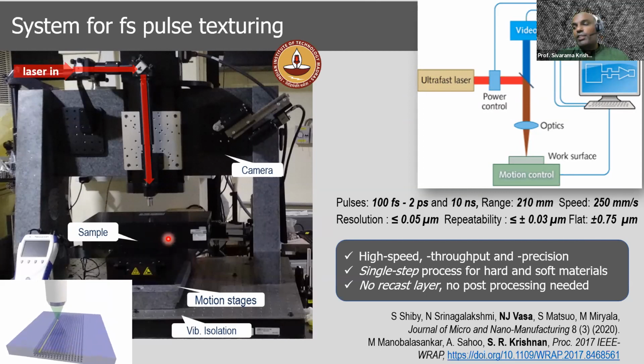These stages may not be very visible on this view graph owing to the fact that they are all black in color, but it's just a conventional XYZ stack. The same schematic is portrayed more clearly on the top right box. So we can vary pulse widths going all the way from sub 100 femtoseconds to 2 picoseconds. In some cases, we have used nanosecond pulses. That's from a different laser in a different lab with Professor Nilesh Vasa. Our stages are fairly precise, but can also be moved at fairly high speeds, 250 millimeters per second. Their resolution is sub-micrometer and they're very repeatable.